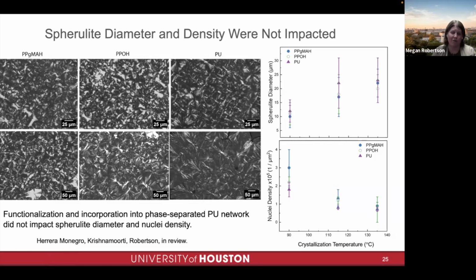Basically not on any length scale, whether we look at the unit cell, the lamellar features, or now the spherulites. It's acting like polypropylene would. And so essentially we think it's excluding those crosslinks into the amorphous regions. There's a little bit more amorphous content, but the polypropylene-rich regions are crystallizing like they would if they were just neat polypropylene.